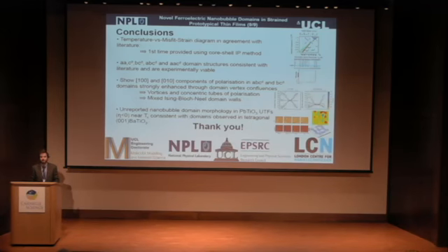I remember when we were looking at this nanobubble in PZT, for instance, we find that sometimes they form arrays, hexagonal arrays. Did you have also like that in the simulation, some kind of self-organization between the nanobubble domains? For the smaller cells, that seemed to be how it was. But that's why I increased the simulation size, because I wasn't sure if it was an effect of periodic boundary conditions. It seems to be a little bit random.